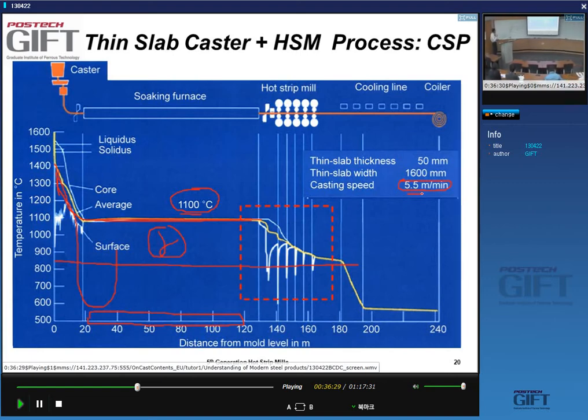If you have 6 meters per minute, and say you're casting something that's 60 millimeters thick, and you end up with a product that is 6 millimeters thick, then you know that the exit speed must be 10 times that value, right? Because the process is continuous. So I have 60 meters per minute, which is basically 1 meter per second, right?